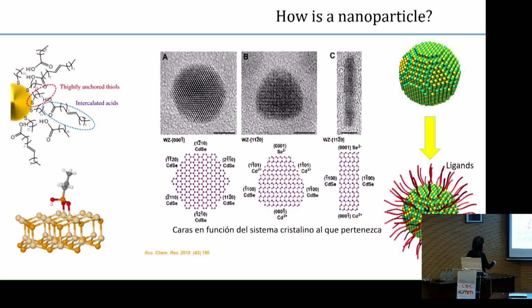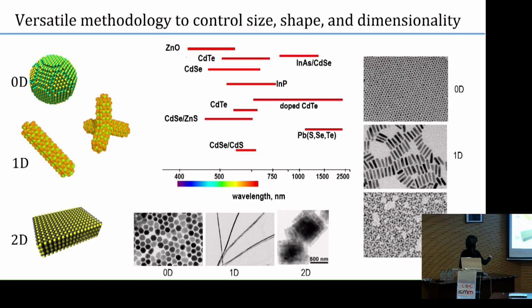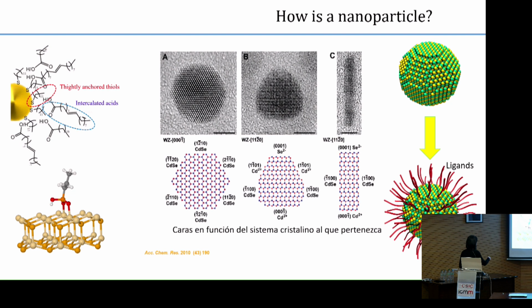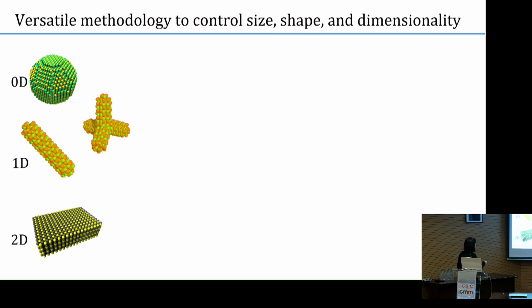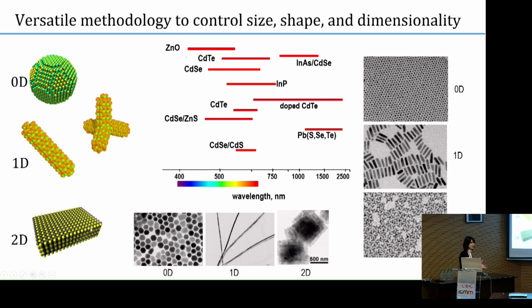So, understanding how these ligands attach to the nanoparticle surface, how they passivate the surface, from different perspectives, from analytical tools, surface science techniques, theoretical models, is really, really important in order to control not only the size, but also the morphology of these systems and the dimensionality. Because nowadays we can produce not only quantum dots that are zero-dimensional, as you can see here, but also one-dimensional or two-dimensional systems and combinations of different semiconductors, in such a way that we have optical responses in the UV, visible, near-infrared and mid-infrared ranges of the electromagnetic spectrum.